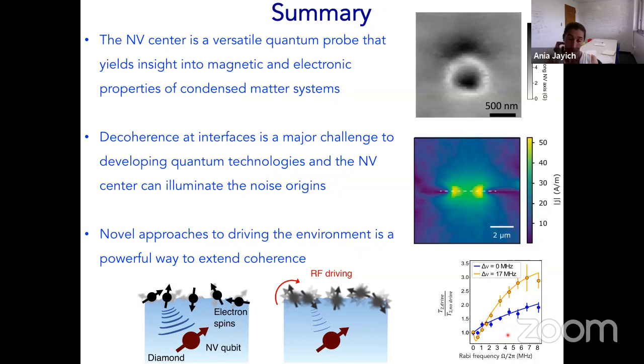Okay, so how good is dynamical decoupling at decoupling electric field noise from magnetic field noise? I think that's a bit of a complicated answer, because first of all, how affected you are by electric field noise or magnetic field noise to begin with depends very sensitively on what magnetic field you're working at, and what transition, if you're looking at the 0 to 1 transition or the -1 to +1 transition, what's sometimes called a double quantum transition. And it depends on the spectrum of the magnetic field noise and the electric field noise, which will vary significantly depending on if you're near a surface or away from a surface. So I don't know if I can give one broad answer to that.